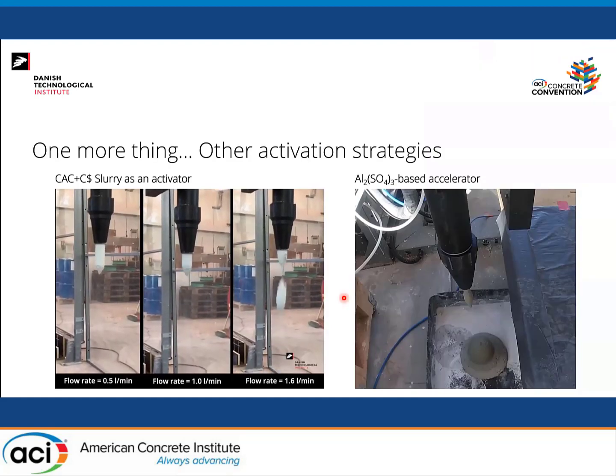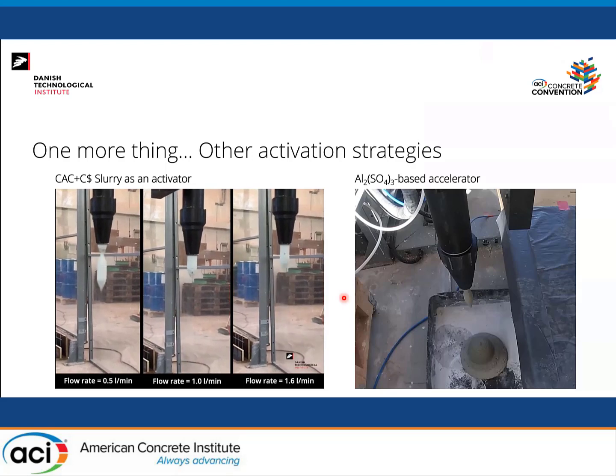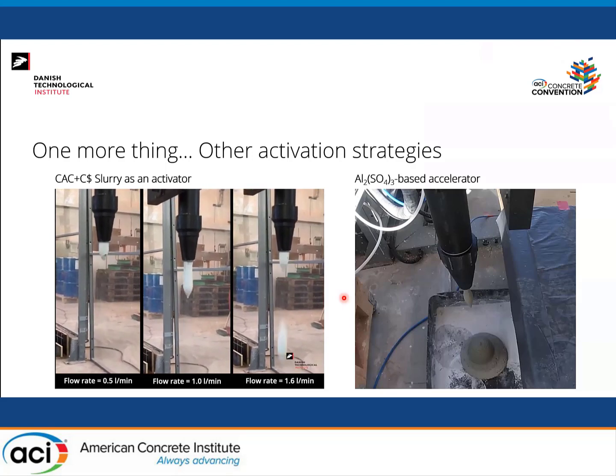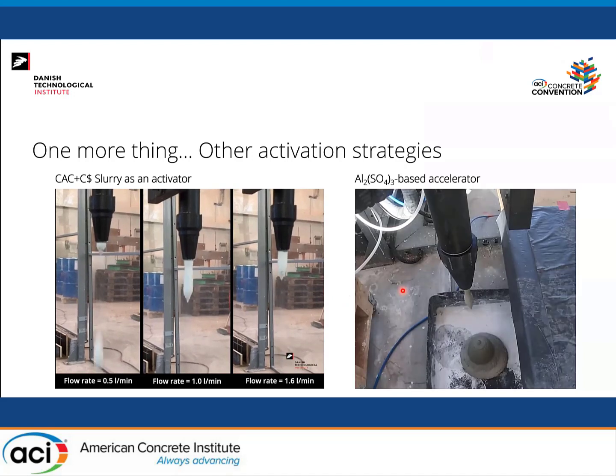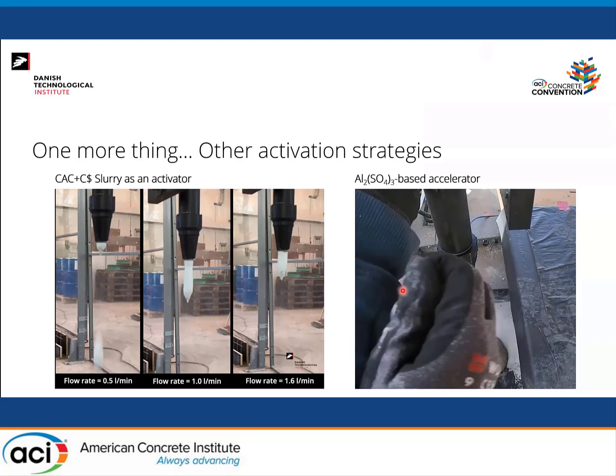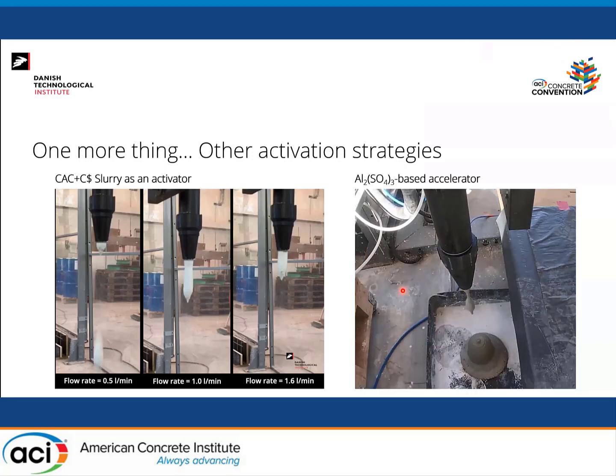Before I conclude, there is just one aspect: I'm talking about activation strategy as CAC and calcium sulfate slurry. That's not the only one. You can also use shotcrete accelerators, but then you will see changes in rheology at the moment my colleague Thomas is opening the injection of the shotcrete accelerator. Within a few seconds, you see the change of the shape of these drops. It's a good indicator of the yield stress of your material. Within 20-some seconds, you see the change of this shape, these drops being extremely little, and then they will be elongating over time, because the accelerator is acting, and that's when we are ready to print. Just to show that there are several strategies you can use for accelerating a mix, so that's not the only one.